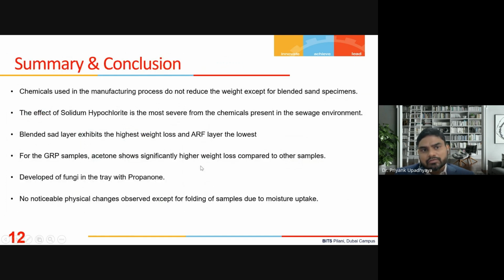So what is the summary from this? We can say that the chemicals we are using for manufacturing processes are not reducing the weight, and mostly this is happening because MEKP is a curing agent. When we expose these samples to MEKP, polymerization may start to happen and new bond formations may occur, and that's why there could be some weight uptake or weight increase. A similar thing can be said for the accelerator and catalyst.